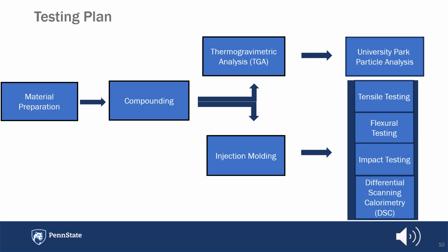In order to assess and compare our material, we followed a very specific testing plan. Within this testing plan, we prepared our material, and from there we compounded it. We ran thermogravimetric analysis and injection molded all of our parts. After running TGA, we sent our 3 types of calcium carbonate out to University Park for a particle size analysis to be completed. After injection molding, we completed tensile testing, flexural testing, impact testing, and ran differential scanning calorimetry, also